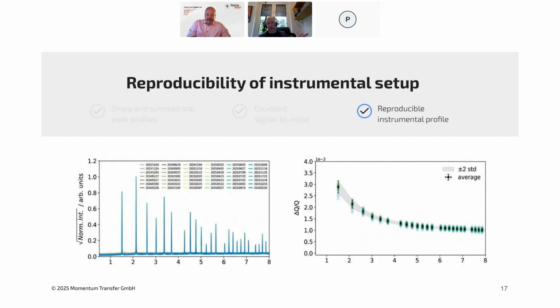But we also have a very systematic experimental setup that we run basically every 2 weeks. And this is very highly controlled in terms of all the motor positions, in terms of the wavelengths used. And so we get a very reproducible signal for our reference materials and a very consistent instrumental profile. So this means that it's very easy to compare data across different beam times directly, as opposed to other cases where you might have to do a lot of extra data massaging to be able to directly compare the data.